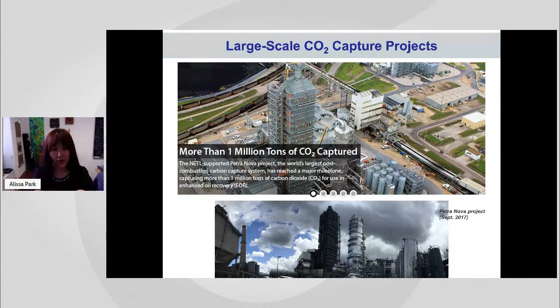If you look at the bottom figure, this is not even the full scale. It's a pilot scale demonstration, but still large enough so that we can learn a lot about these systems. One reactor is a CO2 capture reactor. Again, the second reactor is a solvent regeneration reactor. As you can see, the reaction kinetics of capturing CO2 is fast enough. Selectivity is great, and moving these liquid solvents around was relatively simple. Reactor design was relatively simple. So we were able to go from lab scale all the way to this pilot scale. But at the end of the day, this is a huge facility you're building, a reactor system, in addition to the power plant or any chemical plant to decarbonize.